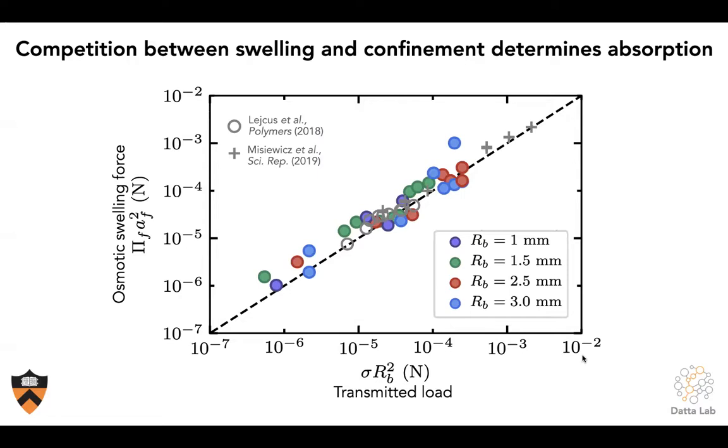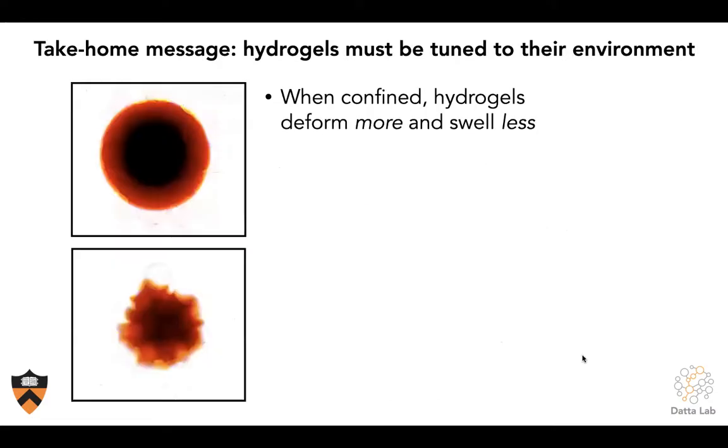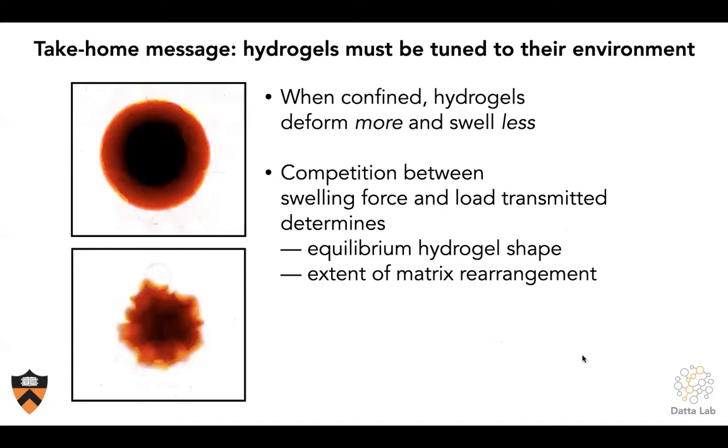So this is just what we've done. A lot of other work in this area, but this is just one small vignette where I wanted to show you how just by watching this process, we were able to find that when these hydrogels are confined, they deform more and they swell less, as you might intuitively expect. But by actually visualizing this process, we've been able to go beyond this simple intuition, quantify it, and show that